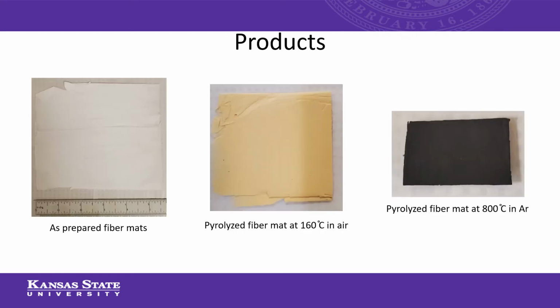Okay, let's look at our product before going deeper. We were able to obtain a fiber mat of approximately 15 centimeters by 15 centimeters, and then we can cross-link it entirely in a low temperature oven at 160 in air. And then we were able to pyrolyze them at 800 degrees Celsius in argon. As you can see, the obtained fiber mats are free of warping, and the shrinkage was about 20 to 30%.